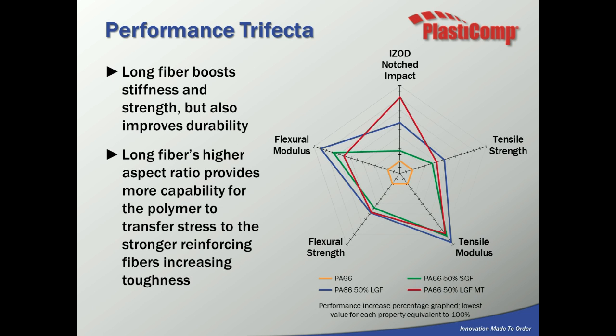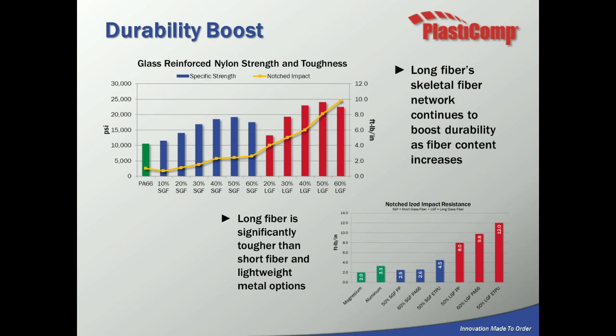So this is a spider graph comparing nylon 6/6 unfilled to short glass, long glass grades. And if you look, I'd like you to look at the blue line, which is signifying a 50% long glass PA66. And as you can see, it has the best balance of performance, whether it comes to strength, stiffness, and then impact resistance when compared to short glass materials.